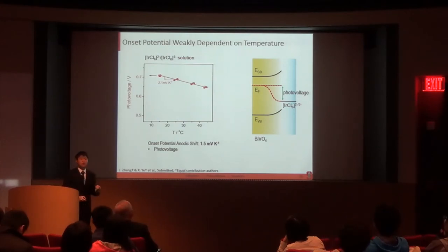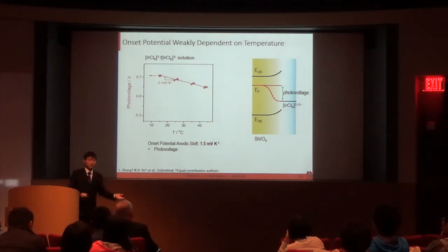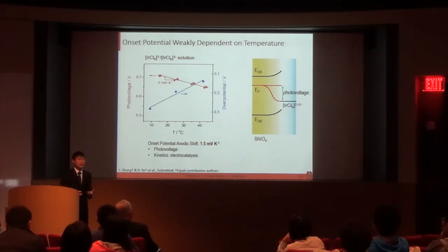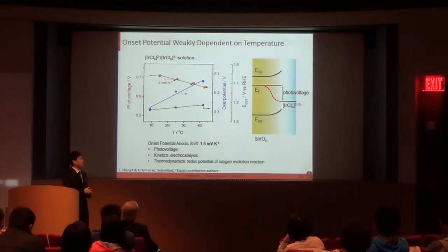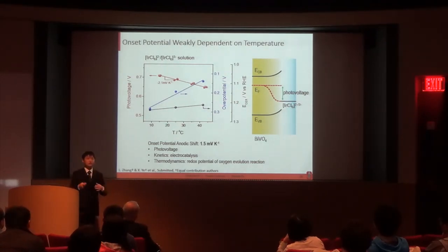And the photovoltage in BVO drops at a rate of 2.1 millivolt per Kelvin. This is consistent with most semiconductors, but this value is larger than the onset potential shift. And this can be explained first by the kinetics. Increasing the temperature improves the reaction kinetics, and therefore the overpotential drops with temperature. And second, thermodynamically, the redox potential for water oxidation also decreases with increasing temperature. So the combined effect of all these three gives rise to a weakly dependent onset potential with temperature.